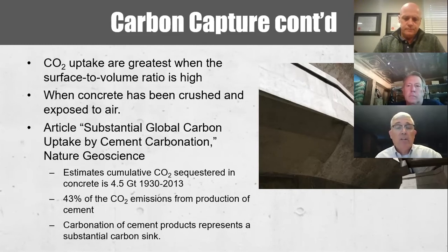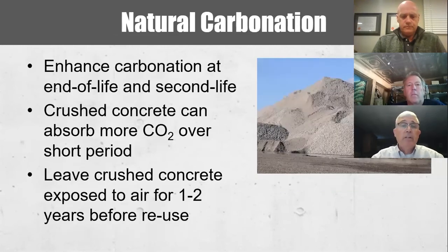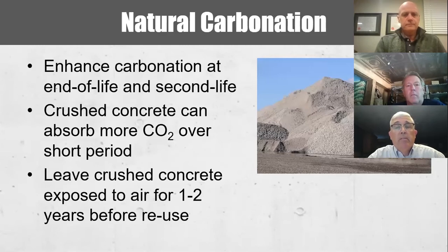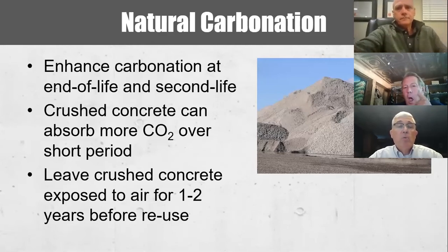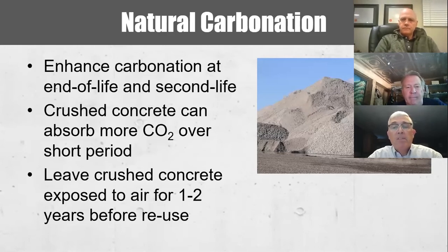So basically, we're looking at carbonation of cement products representing a substantial carbon sink and a game-changing development. And our industry continues to investigate ways to accurately quantify this process, which will then impact the understanding of concrete's role in permanently helping to reduce greenhouse gas impacts. As I mentioned, the best type of concrete for this natural carbonation process is crushed concrete, which can absorb more CO2 over a shorter period because you're maximizing the surface area of the material, so it can be more effective in that absorption.